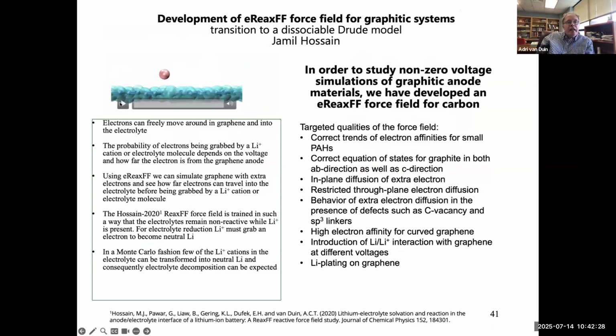So coming back to graphite, we managed to develop this a couple of years ago for the lithium graphite system for batteries, where we actually can really simulate the electron transfer at the anode. So we start here at the bottom with a graphitic anode. Every carbon has 1 electron. We add 1 extra electron in the graphite, so this is essentially a -1 graphite. The lithium cation here in pink comes close to the graphite, so this is a lithium plus. And then after a little while, that extra electron finds the lithium and jumps to the lithium, makes a neutral lithium. And now this neutral lithium can make lithium metal. So we have a real electron transfer event now, and that's clearly very important.